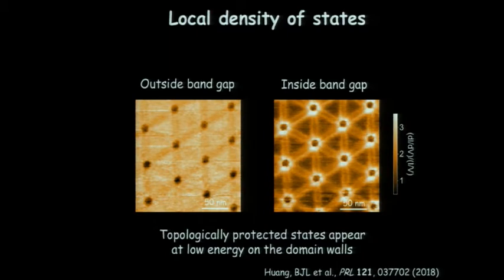Have you checked a little bit this strain dependence of all of this? We tried the same kind of things with the hBN, and we didn't see much going on here. We never were able to see the same kind of strain effect. And we tried that same thing with just graphene on silicon oxide and weren't able to do it there. There seemed to be something special about the boron nitride.